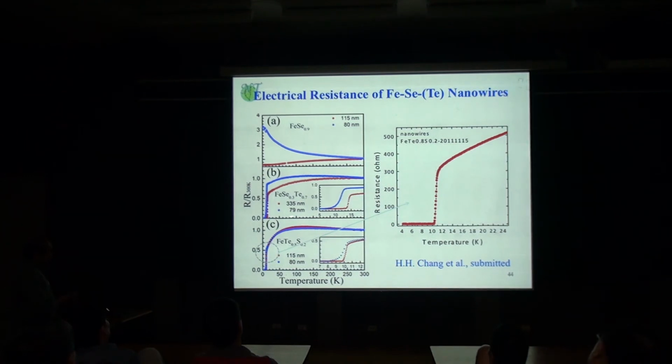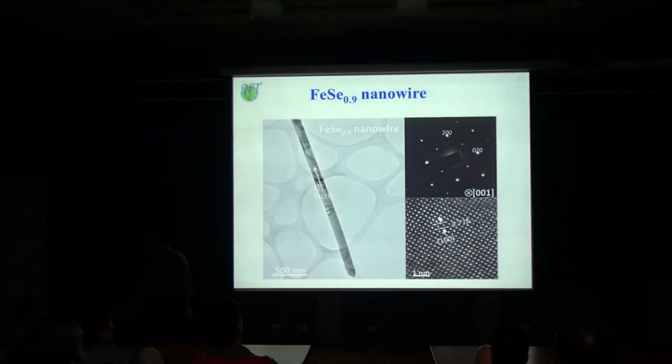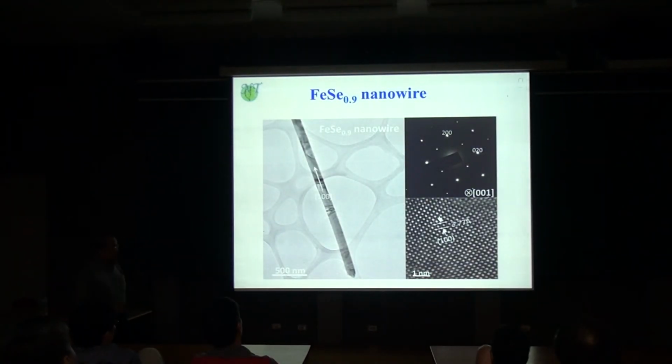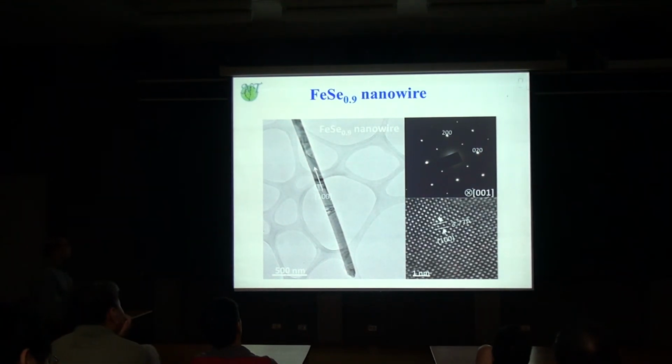The transitions of those that were superconducting were very beautiful. The TC was very sharp. I mentioned it in a paper. So we have to look at what we have. From the structure, the TEM, you can see that very nicely. And the diffraction shows that we all have perfect tetragonal symmetry, but one is not superconducting. More detail, and then you analyze it.